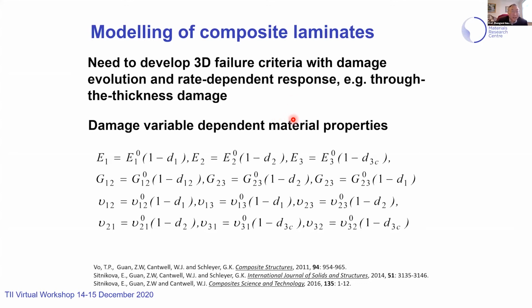Here is the degradation of material stiffness. We have the modulus related to damage variables. These damage variables change from 0 to 1, and then you can imagine the stiffness matrix goes close to 0. So you lose load carrying capacity, and that element will be removed.